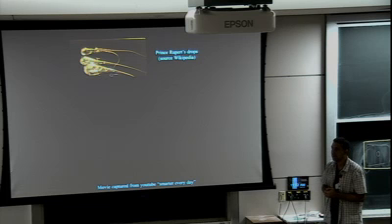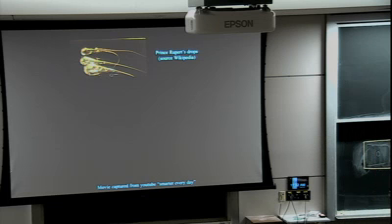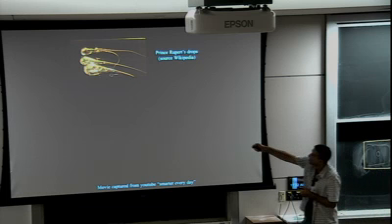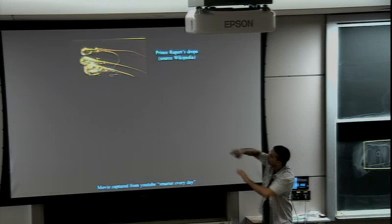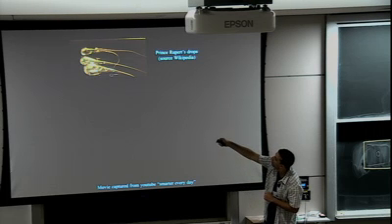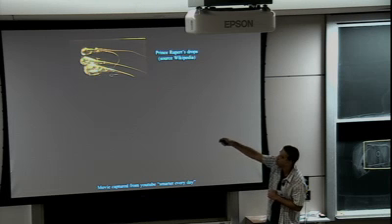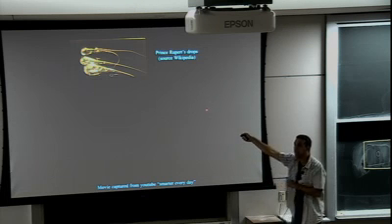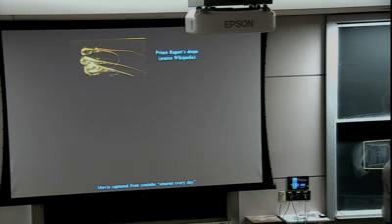And you can see by the fringes here, in a polariscope, that the residual stress actually extends into the tail. So the inside is under tension, the external area is under compression,